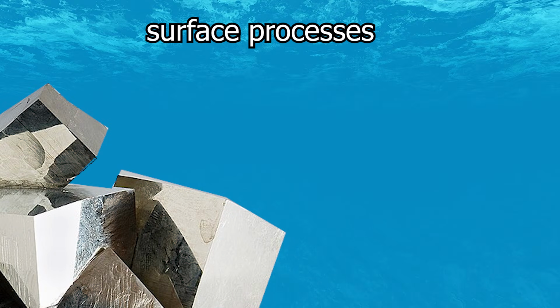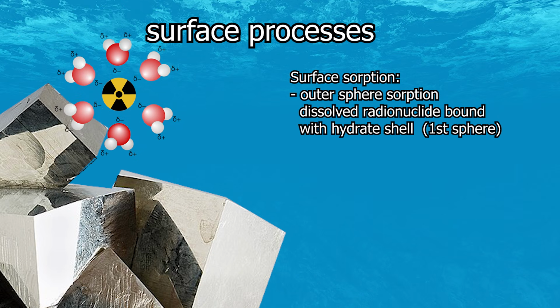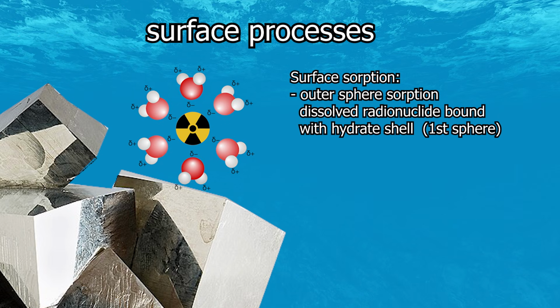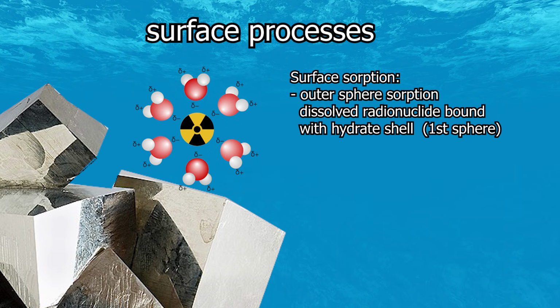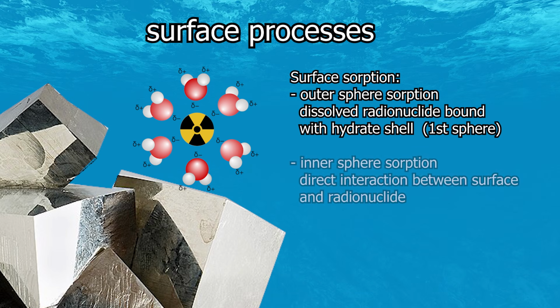Now back to the immobilization. The weakest type of immobilization is surface sorption. But even here, there are different degrees of interaction. In the simplest form, we have a hydrated radionuclide that can be held electrostatically together with its hydrate shell onto the surface. This so-called outer sphere sorption is based on van der Waals forces and therefore is not particularly strong.